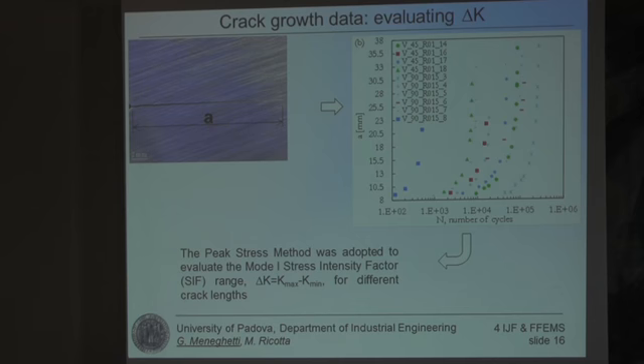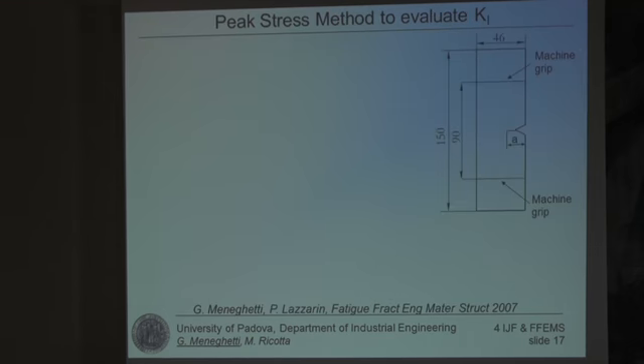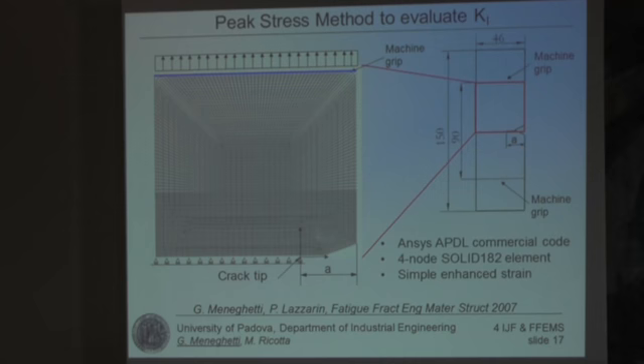We performed additional standard experiments with the crack propagation monitoring, so we produced the curves, crack length versus the number of cycles for different applied stress levels, and we calculated the mode 1 linear elastic stress intensity factor for each crack length. In view of this, we applied the peak stress method to speed up the calculations. We presented this method about 10 years ago, and we were inspired by the Japanese school in this case. The concept is this one.